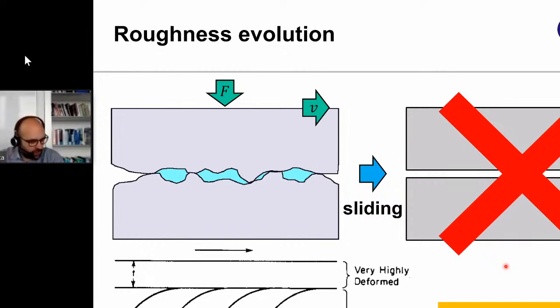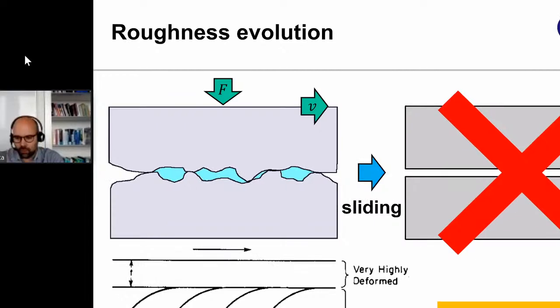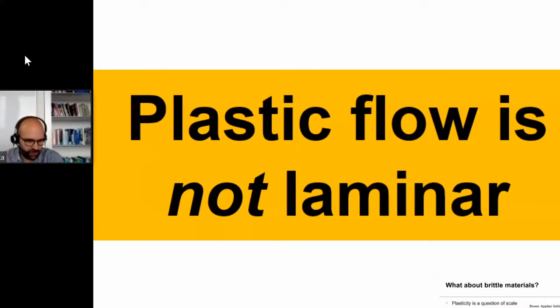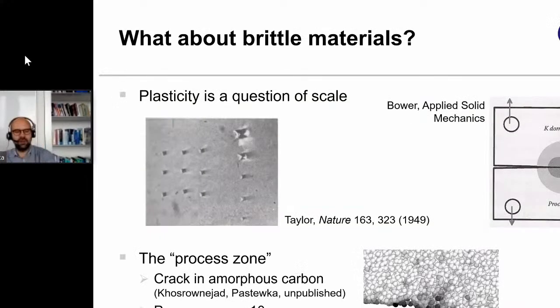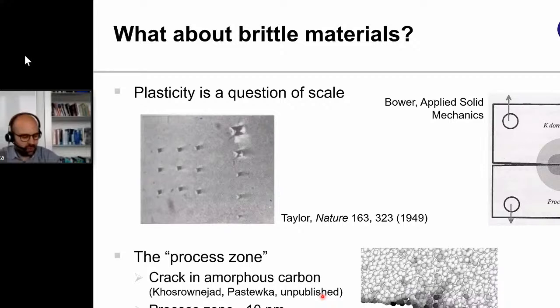Let me, for the last couple of minutes that I have here, talk about brittle materials. So this is, of course, a mechanism that depends on plasticity. What happens if the material is brittle, if we have cracks in the material? The first point that I want to make is that plasticity is a question of scale. This is a picture taken from an old paper, 1949, in which Taylor did the indentation experiment and noticed that with very small indents, this was a glass, I think a soda lime glass, the glass behaved perfectly plastic, and for deeper indents it would fracture.